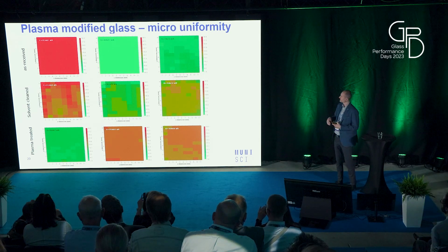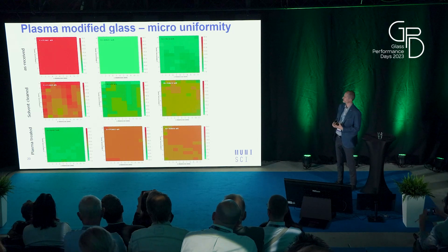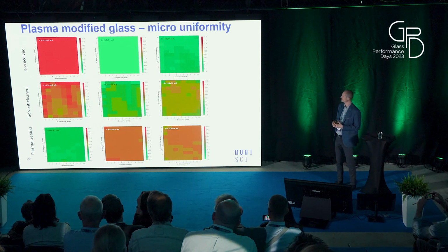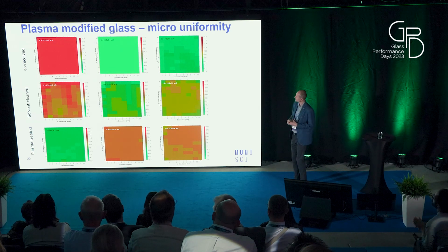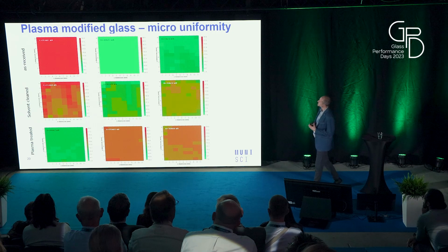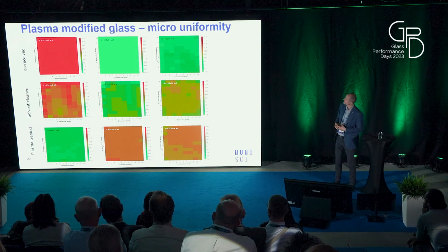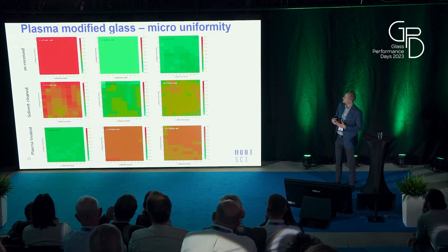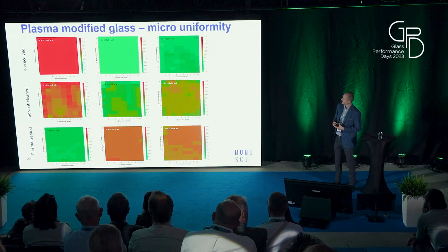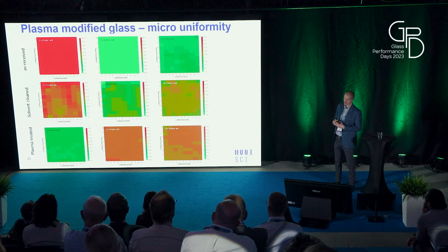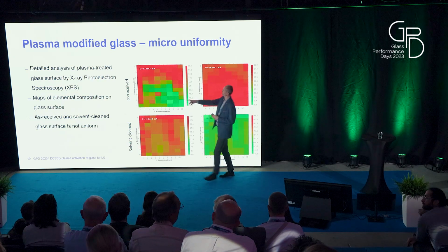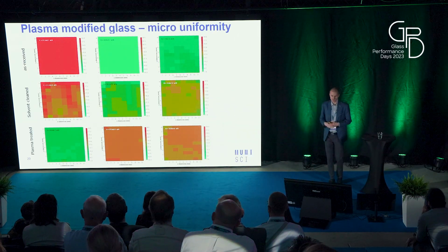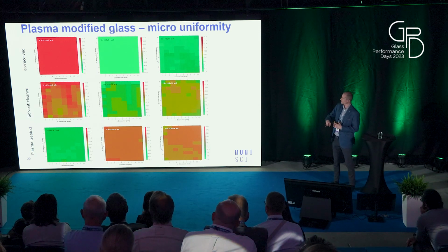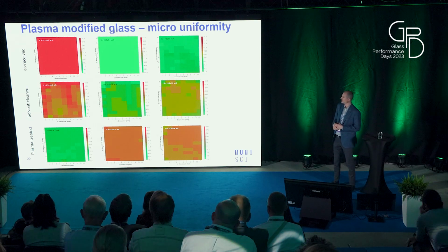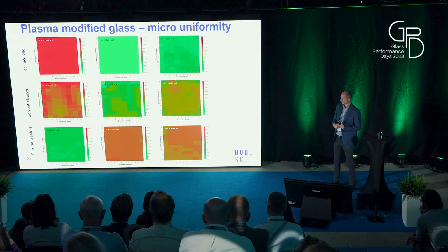And here in this slide, we have a comparison of as-received glass, standard wet-cleaned glass surface, and also the glass surface after the plasma treatment. The scale of this graph is the same, and you can see that if we discuss only the carbon concentration, in the first image in the top left corner there is a high concentration of carbon. This one is the same as that one, only the scale is different. And we see that after the plasma treatment, the concentration of carbon decreased to less than 5%, and the surface is very uniform. We see this good uniformity also on the map of oxygen.